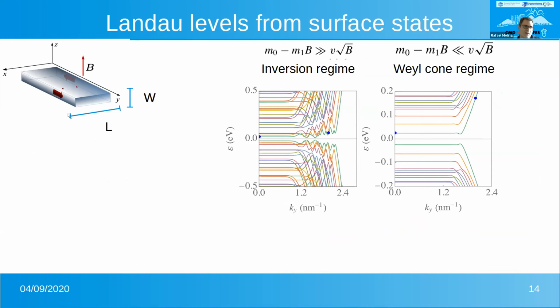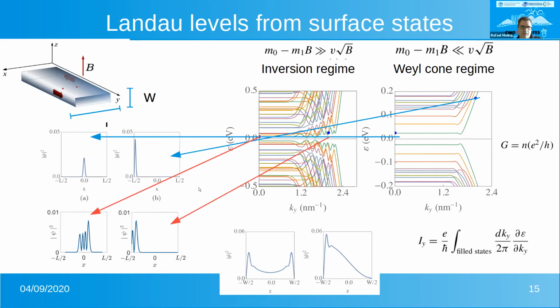Here, instead of a slab, we have a bar with two finite directions. In the inversion regime, the quadratic terms must be much bigger than the linear terms, and there is a whole bunch of very mixed states, where the hole and the particle parts of the bulk are mixing. While in the Weyl cone regime, the hole and the particle parts are very well separated. If we plot the wave functions, you will have a lot of nodes in the inversion regime, while in the Weyl cone regime, you have very nice wave functions that, in this part that is starting to disperse, are localized at the surface.